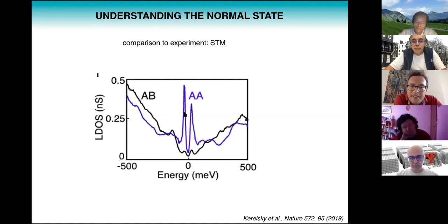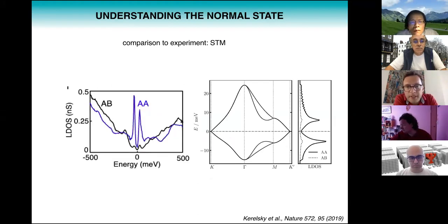And what you see is that there are some very pronounced peaks in the AA regions. And then there are some relatively minor peaks in the AB region. So most people focus on the AA regions. So let's understand these results using our band structure.